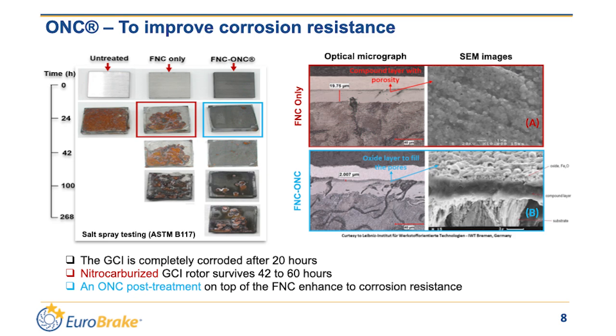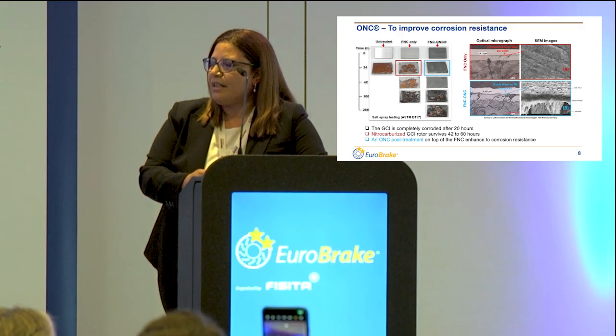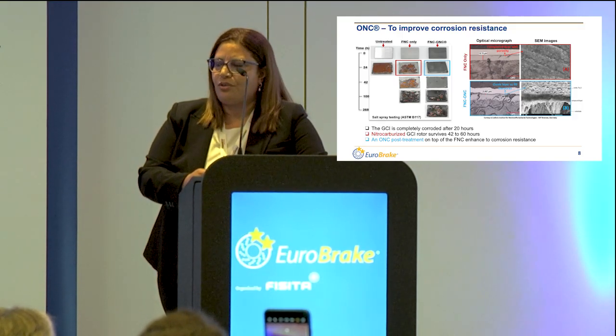To evaluate the corrosion resistance, we performed salt spray testing according to ASTM B117. The results show that the untreated gray cast iron is completely corroded within 20 hours, and the FNC only treated sample survived 42 to 60 hours, but when applying a controlled post-oxidation, the corrosion resistance was enhanced. And we can explain this by scanning electron microscope.